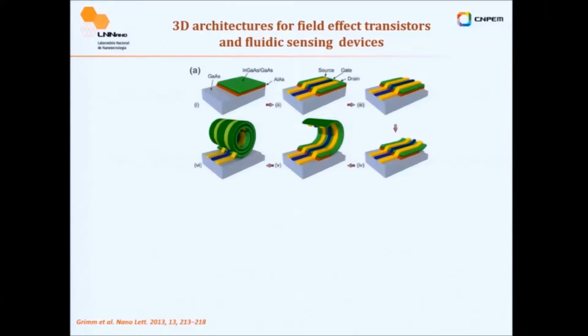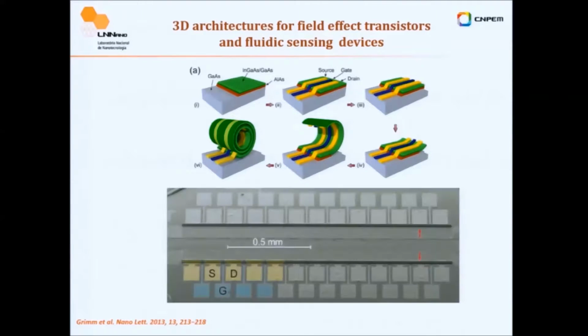The difference is that we built a field effect transistor on top of this layer, and after you roll, your contacts are embedded in the system. So you can see a source, drain. Maybe in this picture you can see our tube, different source, gate, drain. Then again, this can be a source, gate, drain. So you have a long tube with different transistors built in there.